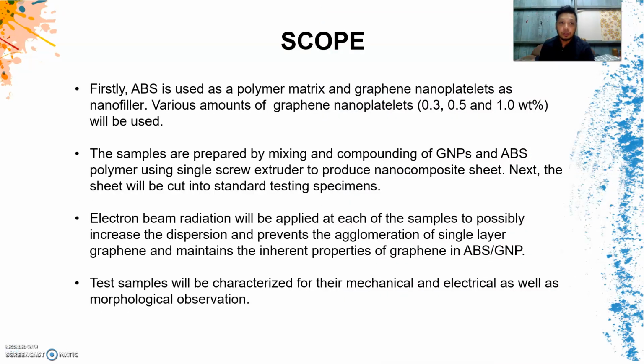Now the scope. Firstly, ABS is used as the polymer material and graphene nanoplatelets as the nanofiller. Various amounts of graphene nanoplatelets, 0.3, 0.5 and 1.0 weight percent, will be used. The samples are prepared by mixing and compounding GNP and ABS polymer using a single screw extruder to process the nanocomposite sheet. Next, the sheet will be cut into standard specimens. After that, electron beam radiation will be applied to each sample to possibly increase the dispersion and prevent the agglomeration of single layer graphene and maintain the properties of graphene in ABS/GNP. The test samples will be characterized for their mechanical and electrical properties as well as morphology observation.